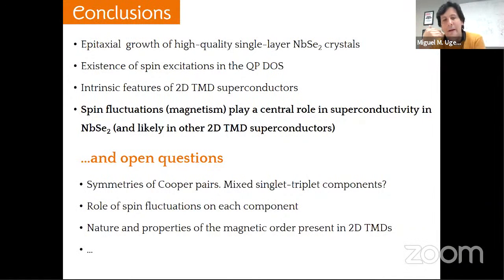For example, the symmetries of the Cooper pairs, if we actually see a mixed singlet-triplet component as we expect in this 2D material. There should also be further work in order to understand the role of spin fluctuations, each component, in the singlet component or in the triplet component, if it exists. And we are also working on trying to understand the nature and the properties of the magnetic order present, either if it's magnetic or it's at the verge of being magnetic.